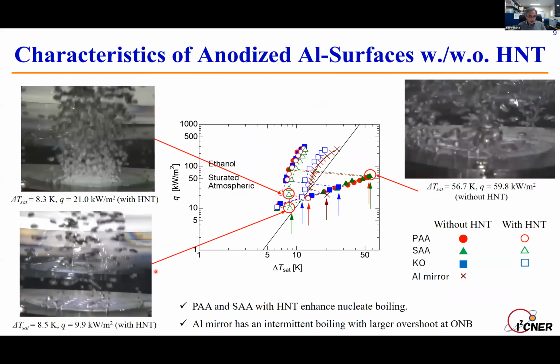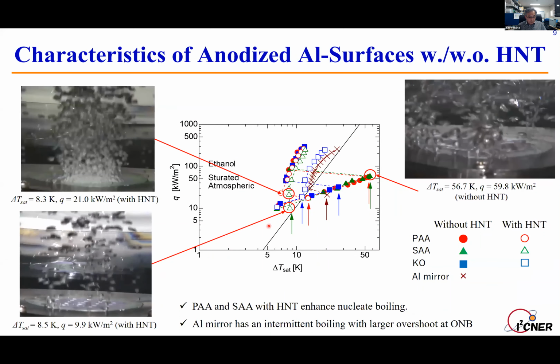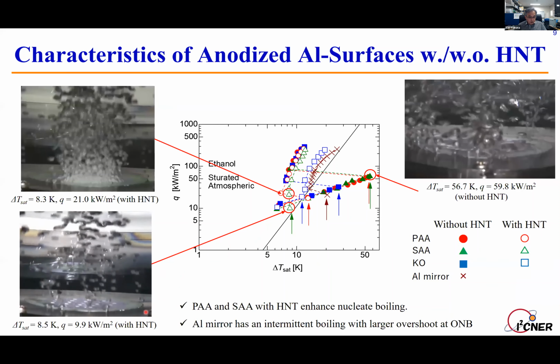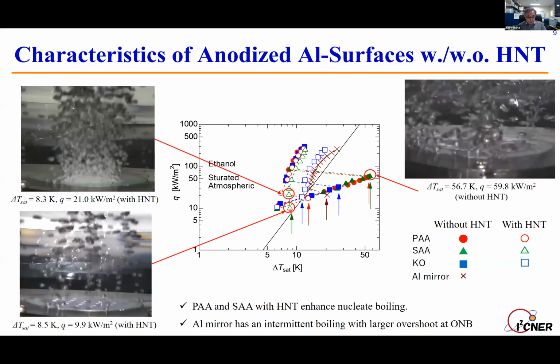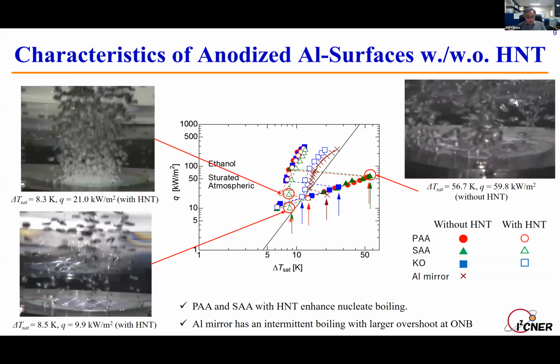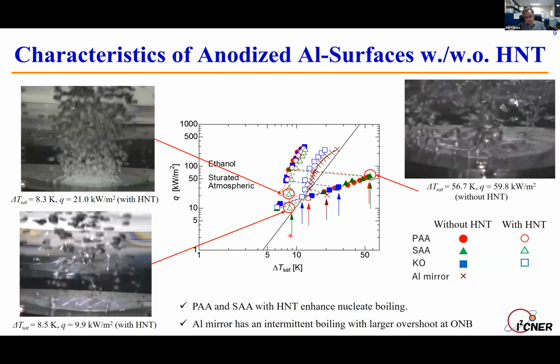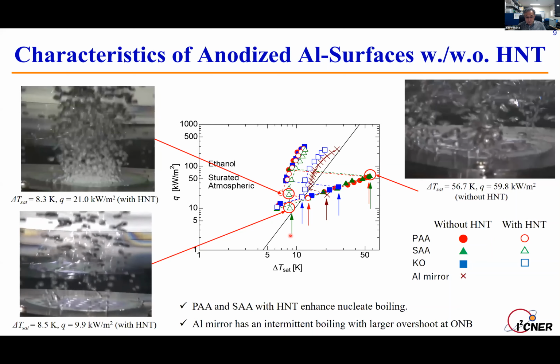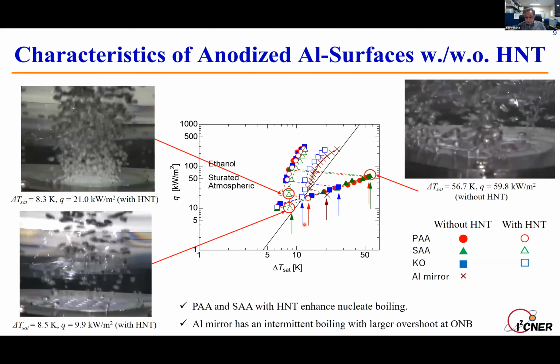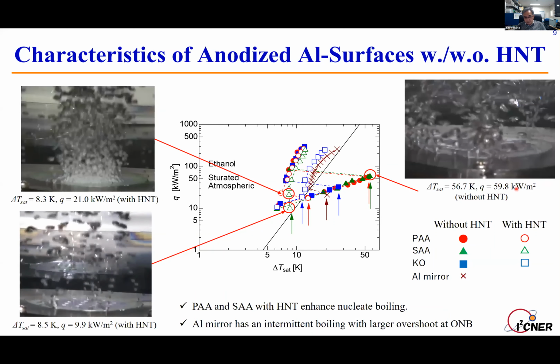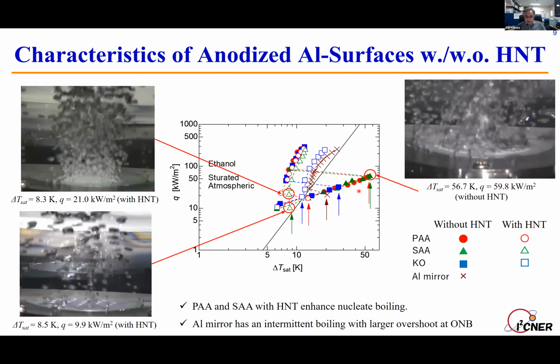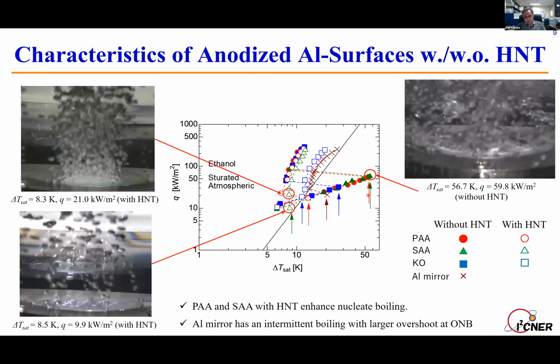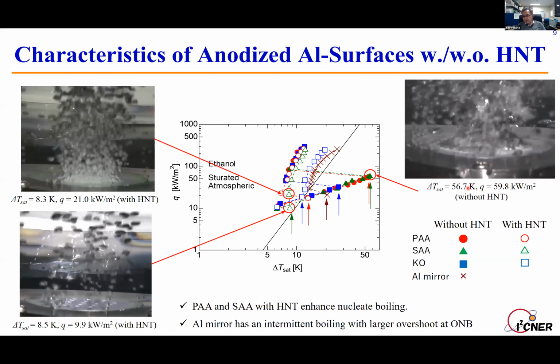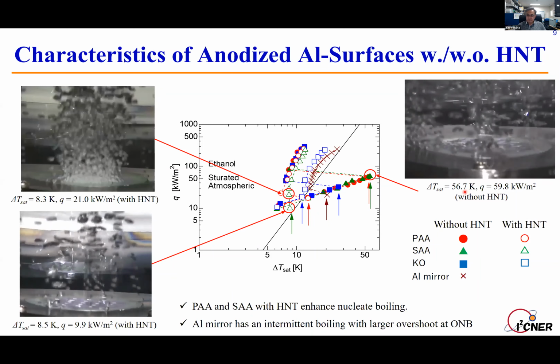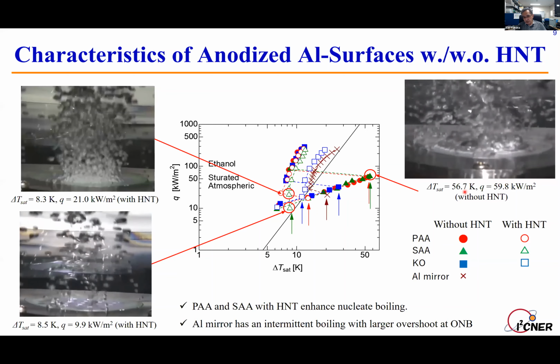So this is a boiling feature on the surface with HNT coating, and boiling starts at a low superheating. But for the surface without HNT coating, in this case, the boiling occurs at a very high surface superheating, 56.7 Kelvin, higher than the saturation temperature.